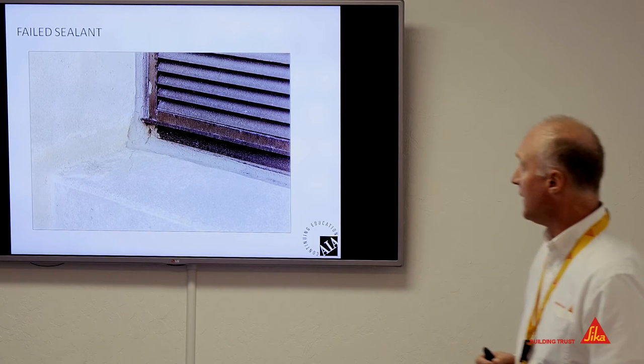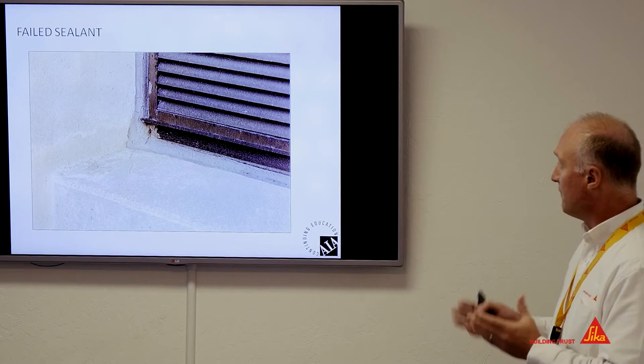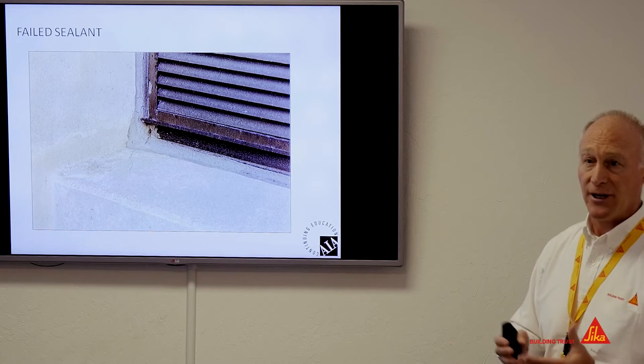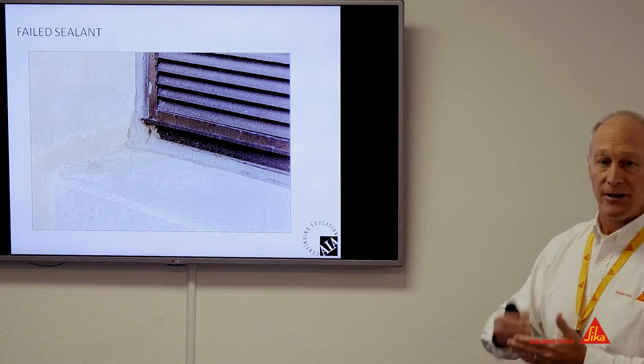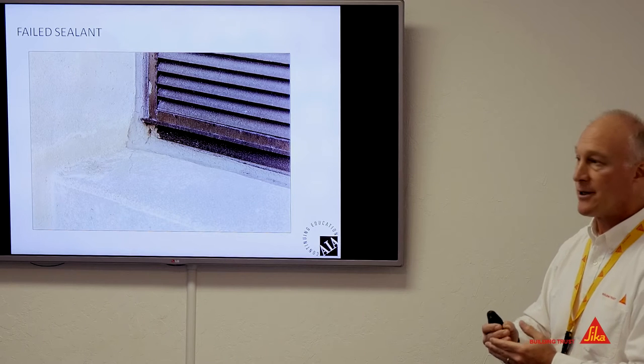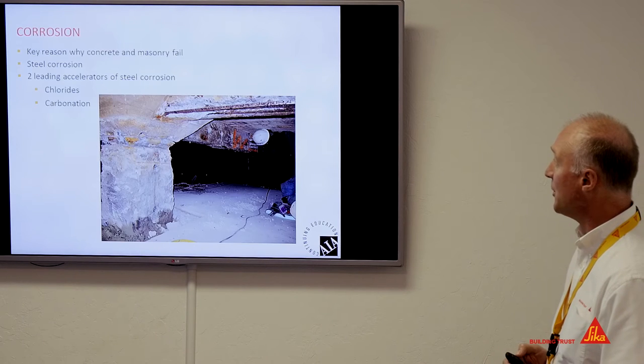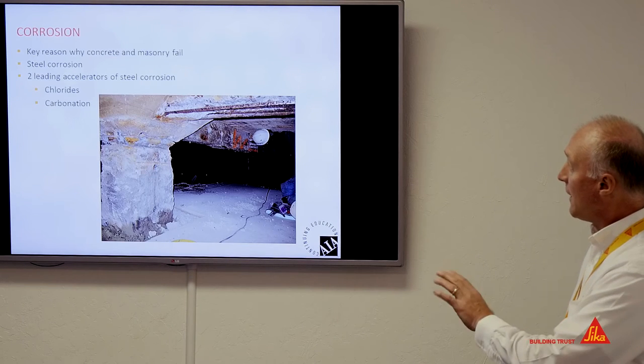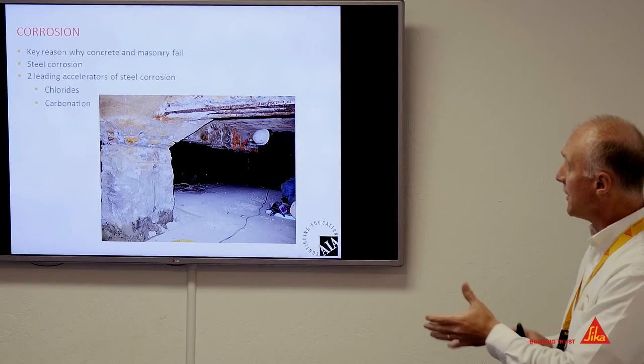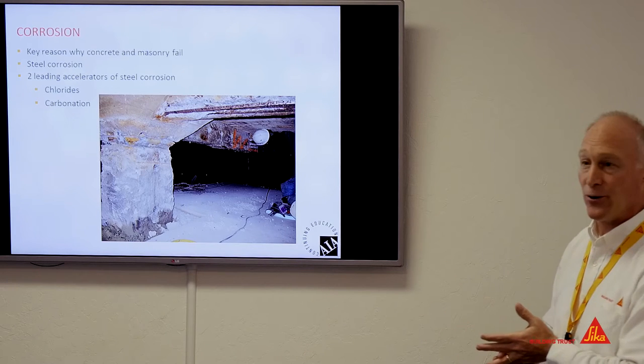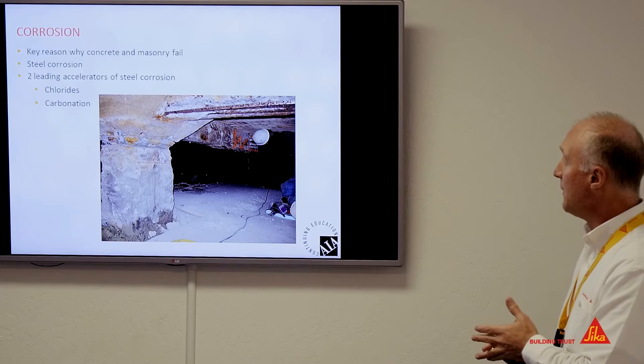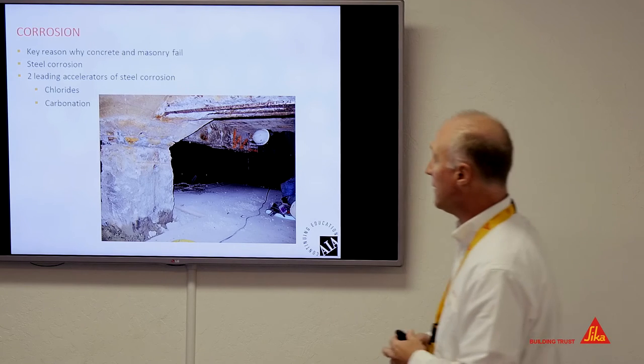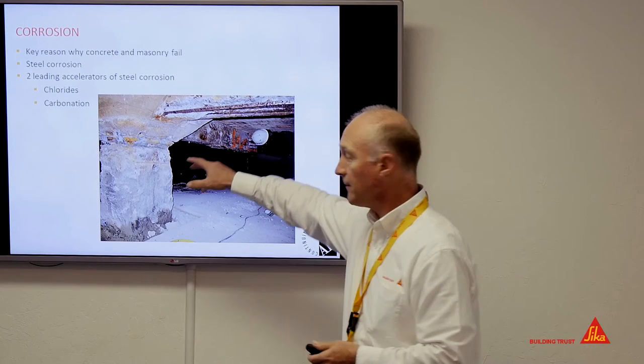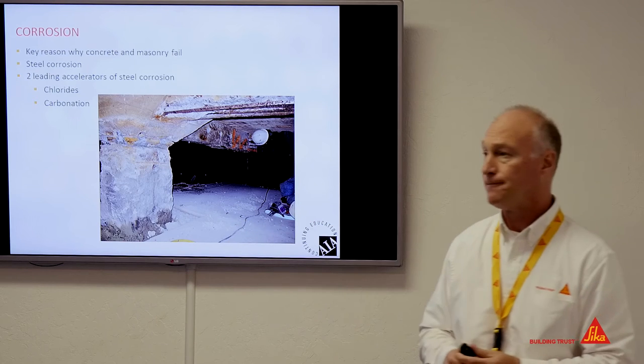Failed joints, failed sealants, we see this very commonly, whether it's around windows or other kinds of penetrations. Again, it's an easy source of ingress of moisture. And really, that's what we're trying to do, is keep moisture out. So what a lot of this leads to, whether it's concrete or masonry, is the steel corroding. And the two leading accelerators of that are chlorides and carbonation.